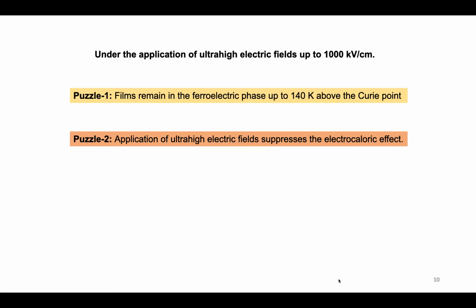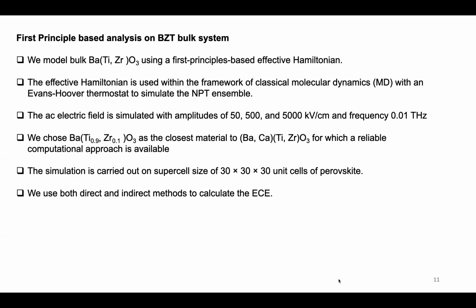So with this, we started doing the simulations using the effective Hamiltonian technique. Here are the computational details. The closest system that we were able to model is BZT, without calcium, that's barium zirconium titanium oxide, with the same concentration. We also were able to have the range of field from very low to very high, going from 50 kV per centimeter to 10,000 kV per centimeter. But I will show the results only for the three important fields.